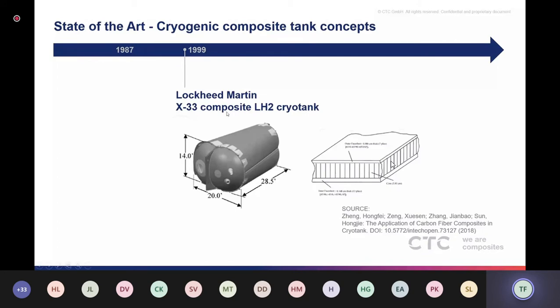During testing, the excessive temperature difference of minus 253 degrees Celsius caused different thermal expansion in the fiber and the matrix material, which caused micro cracks to happen in the inner face sheet. This allowed the hydrogen to permeate through, collect in the honeycomb core, where it evaporated, the pressure increased, and the top face delaminated, and the tank was destroyed. This indicates one of the major problems of composite cryogenic tanks: the occurrence of microcracks in the tank structure, which allows hydrogen to permeate.